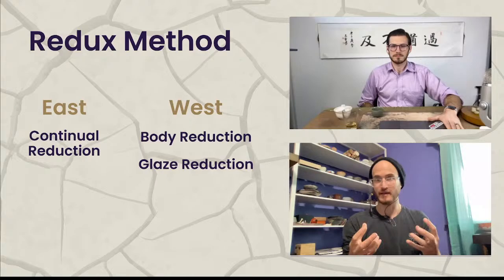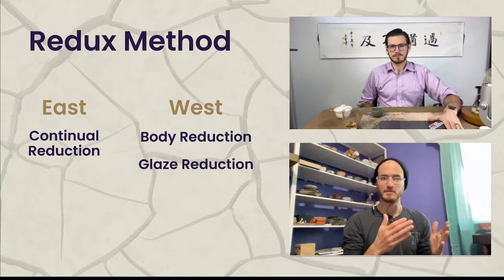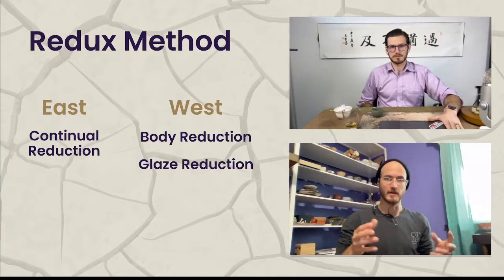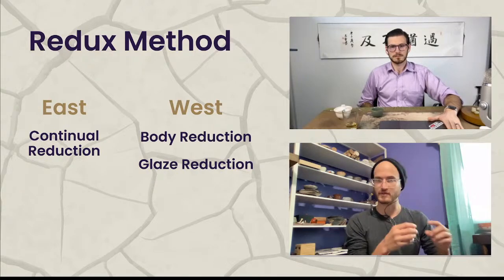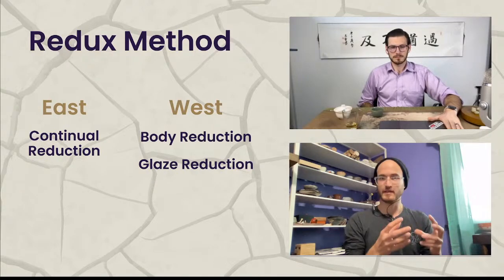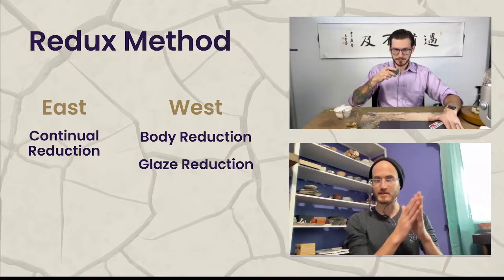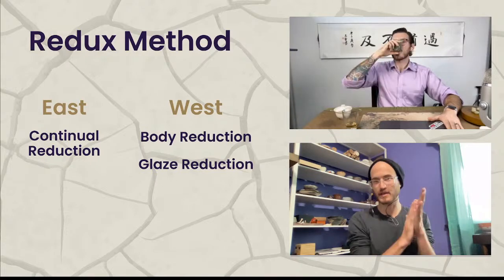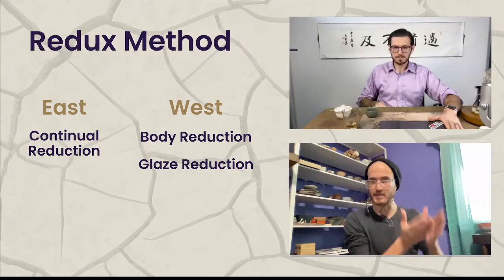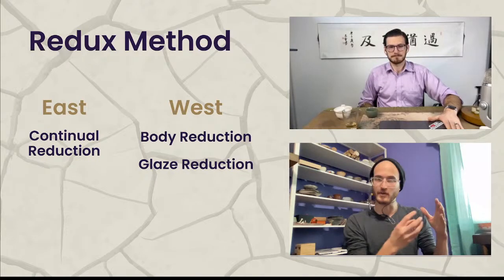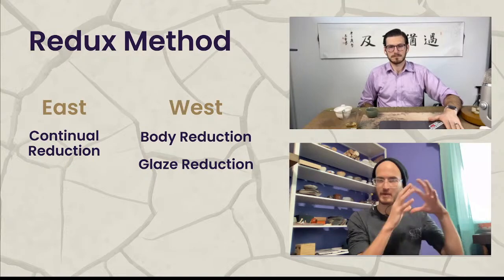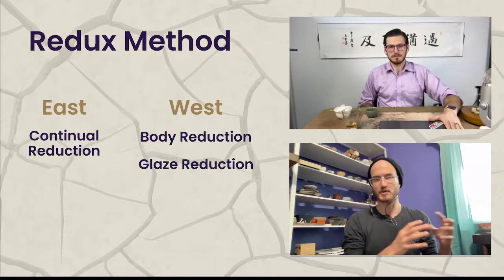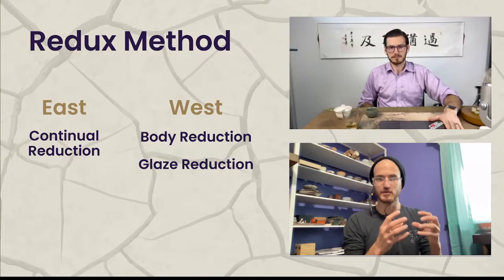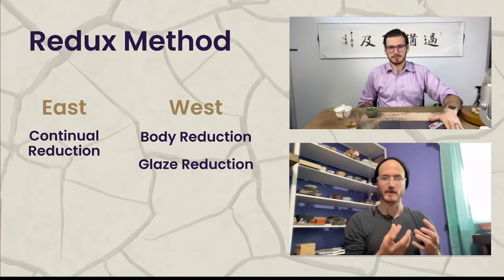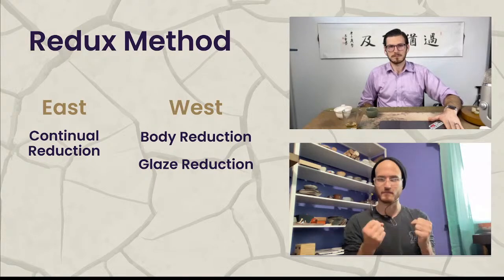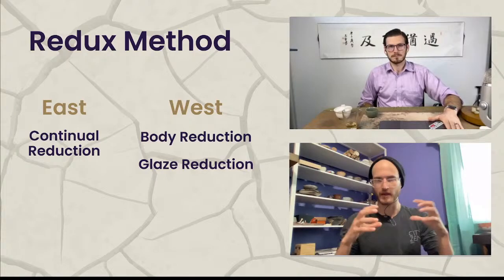And the reason why we do it early is because this is just after when all of the organics have burned out of the clay. So you're less likely to have imperfections from that. And then it's also when the glaze is still a powder. So once the glaze gets to a certain temperature, it seals itself off. And then the clay underneath the glaze is no longer going to be able to be exposed to the atmosphere, right? It's being protected by the glaze. So this early reduction is done to expose all the clay throughout the vessel to reduction and make sure you get that more powerful, stronger melting inside the clay.